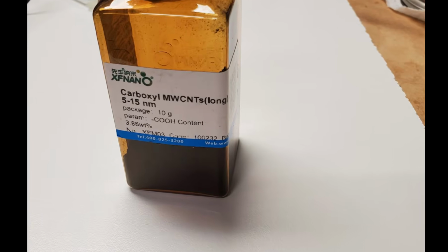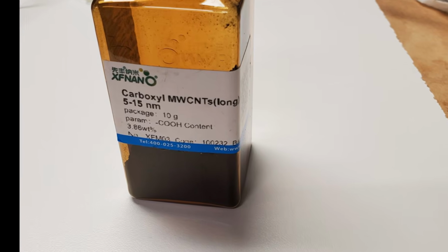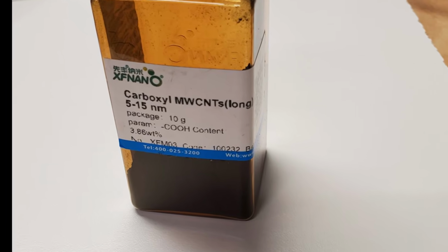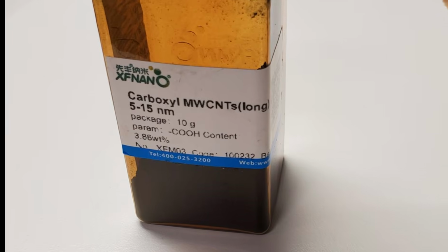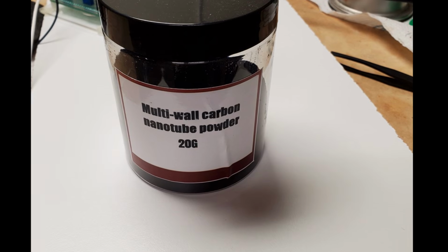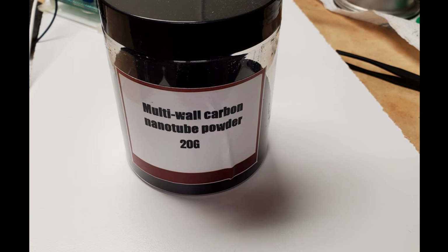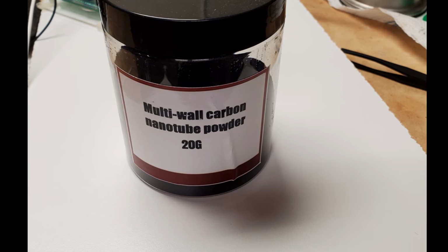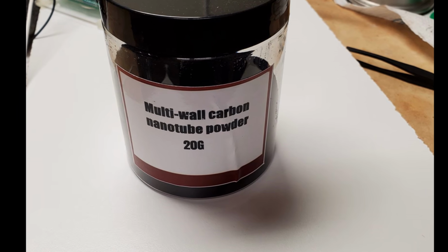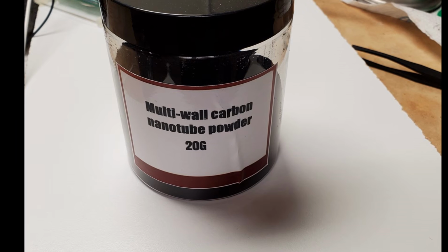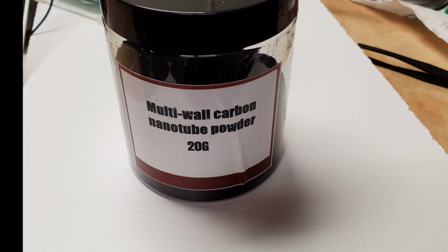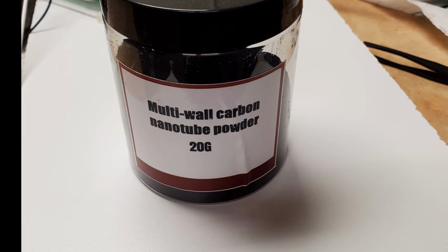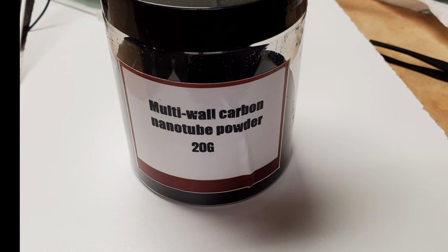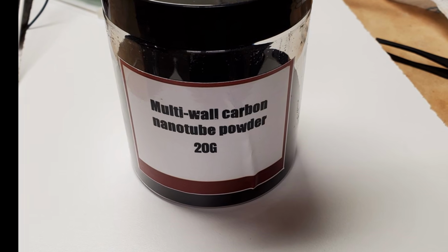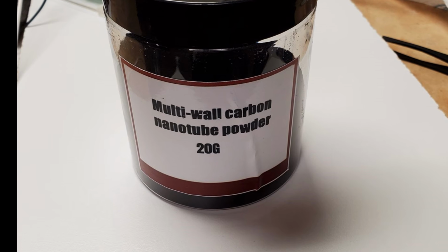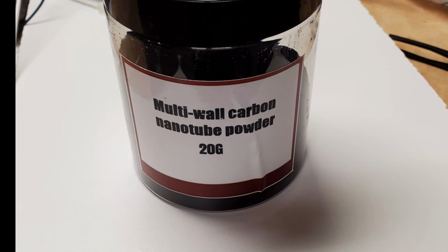Carbon nanotubes are surprisingly easy to obtain. These multi-walled CNTs were available at Amazon. They worked fine. These no-name CNTs can be found on AliExpress. Unfortunately, these CNTs are rather dirty. They first need to be calcined in air to get rid of all the amorphous carbon, and then they need to be washed in hydrochloric acid to get rid of the iron catalyst. However, after the cleaning steps, these CNTs work even better than the previous ones. They are also about 1/3 of the price.